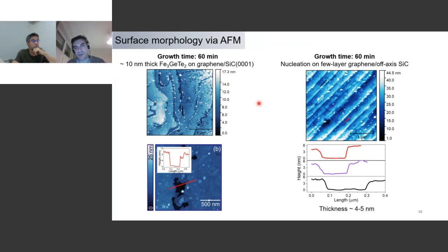We took a sample of silicon carbide that has an off axis. That means we have a miscut in the wafer. This leads to a much higher density of step edges at the surface. And the consequence of having more step edges is that you are able to nucleate graphene layers more easily than in the other case. And this leads to a surface coverage that is not monolayer graphene, but is completely few layers graphene. So that means we have 3 to 4 layers of graphene instead of monolayer on the terraces.